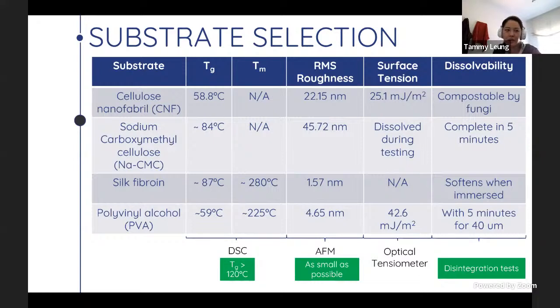thermally unstable. Another very important factor in the building of a transistor is also the roughness of the substrate itself, which can be carried on to the subsequent layers deposited above. Therefore, this value must be minimized. In terms of the substrates chosen here, silk fibroin showed the lowest at approximately 1 nanometer, while others such as papers or cellulose alternatives here showed the highest.